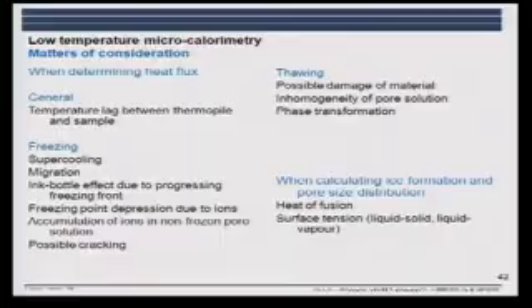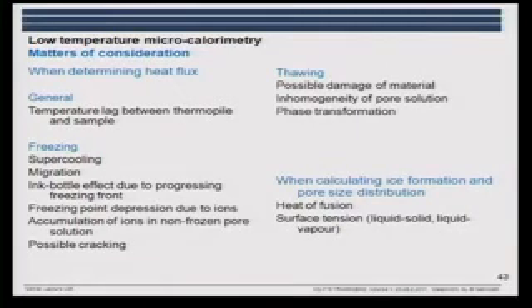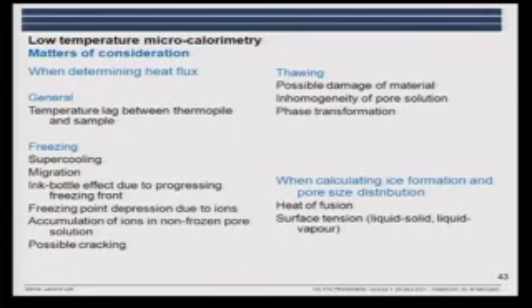There are several matters of consideration. When determining the heat flux, there might be a temperature difference between the thermopile, where you're measuring the temperature, and the sample. And if you have a lot of water which is freezing and the temperature is decreasing at a given rate, well, there will be a temperature lag. Then freezing, you may have supercooling of your water or the pore liquid, and often a nucleation agent is used to ensure that you don't have that much supercooling. There might be migration of water from the interior of the sample out to the surface, so freeze drying.